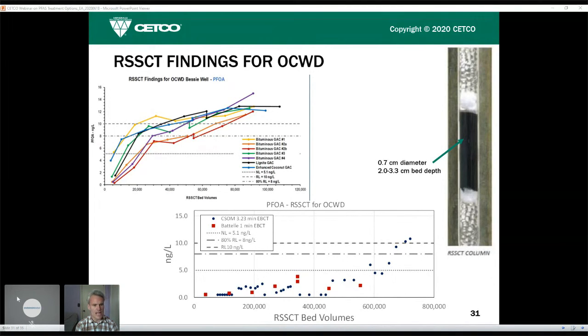And then in the bottom, we have 2 separate experiments that were done for FLUORO-SORB. One was done at Battelle and one at the Colorado School of Mines. For the Colorado School of Mines, we were running around a 3-minute empty bed contact time, and Battelle actually did a 1 minute empty bed contact time. So in these experiments, the water is just screaming through this media. You can see we got to around 600,000 bed volumes for the FLUORO-SORB before we started to hit that 10 nanograms per liter. So about 10 times more bed volumes compared to GAC shown in the top left.